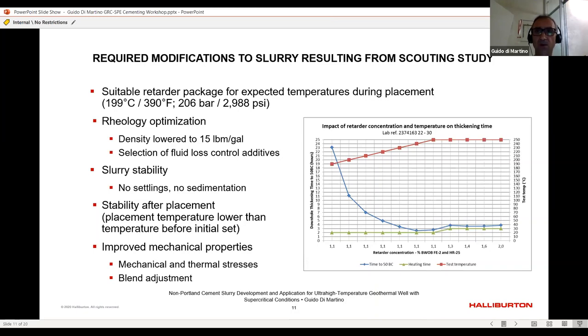Calcium aluminate phosphate, being the best survivor in phase one, was selected with no limitations of the calcium aluminate phosphate system. A decision was made to conduct all thickening time tests at 200 Celsius. This was determined after temperature simulations of the planned drilling operations proved that this temperature can be achieved at the time of cement placement.